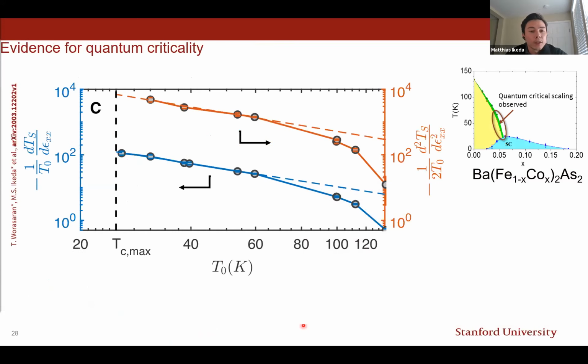And if we now take a look at our data, we can see that for all the materials showing a transition temperature at zero strain lower than about 60 Kelvin, we indeed find such a linear regime in the log-log plot of these two coefficients, the linear and the nonlinear coefficient. And this is a really interesting result.